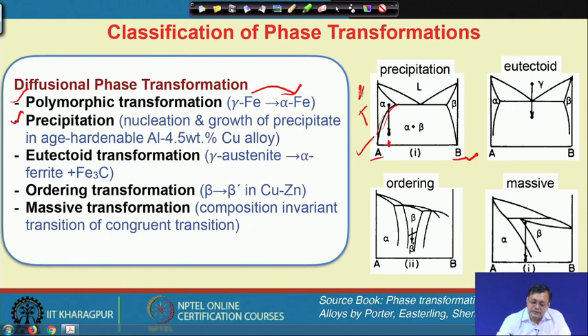Here we can simply choose such a composition and heat it up. This is the temperature axis, and go up to here. Then we will get a single phase alpha. And now, if we quench it, then we can get a supersaturated solid solution, or we can have a slow process where this beta phase will evolve here, and as we cool down, this precipitation of beta will occur in an alpha matrix.